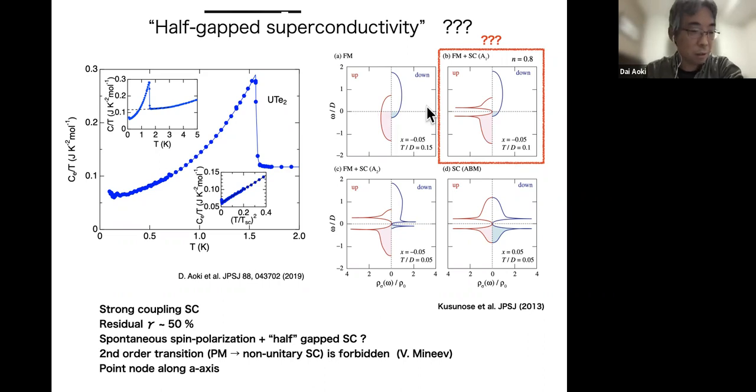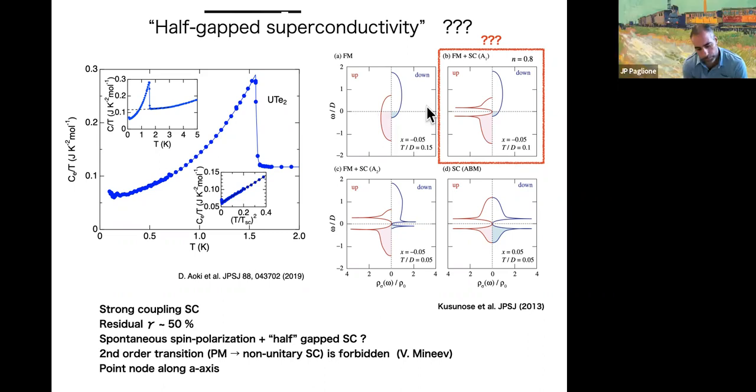I mean, JP, you can confirm, right? This is also confirmed by STM, right? STM doesn't see considerable density of states even at 0 energy, right? Well, the comment I would make is that in all the thermal conductivity we've measured, there's no residual conductivity. So I don't call it density of states, unless it's extremely strongly scattered such that it doesn't conduct heat. I don't know what it is. To me, it's some localized entropy. It's not an electronic density of states.